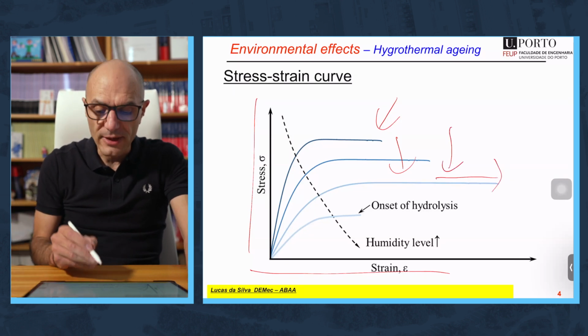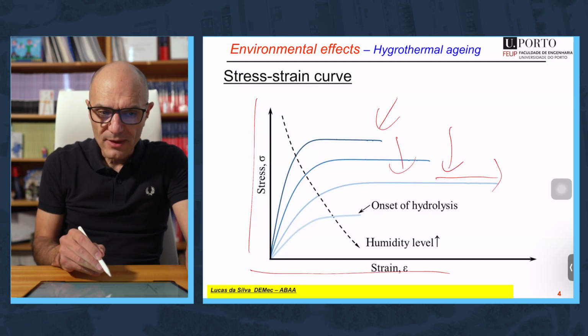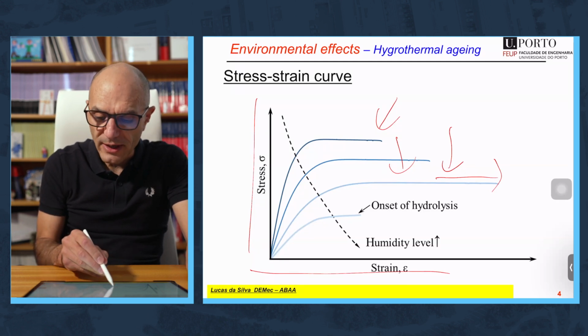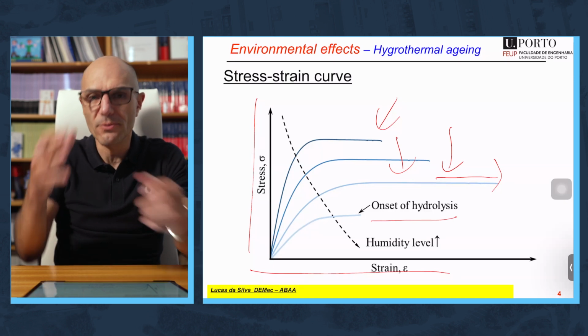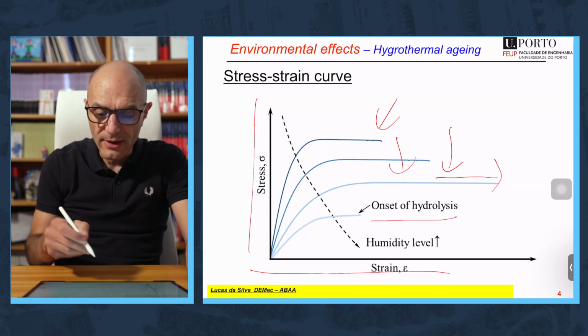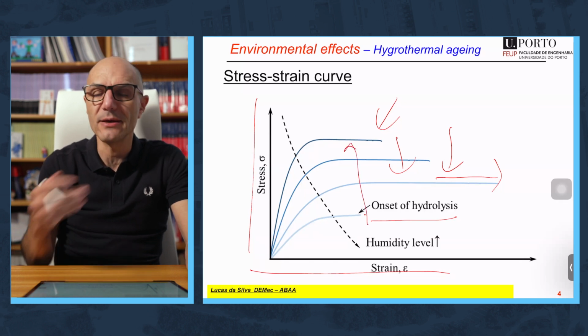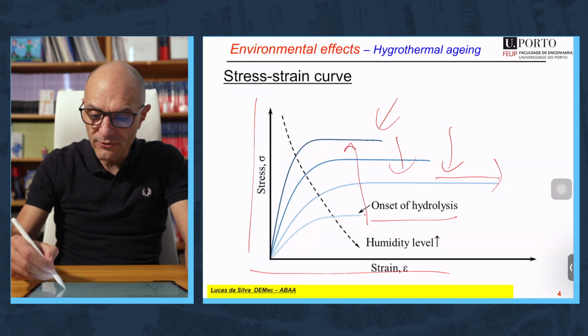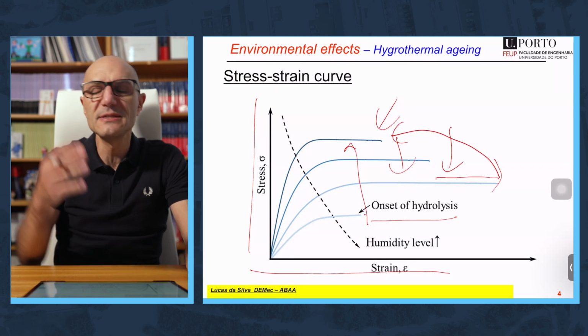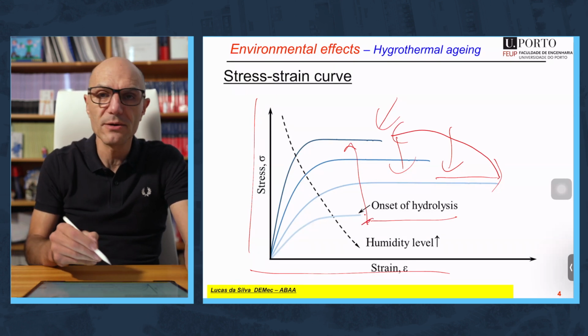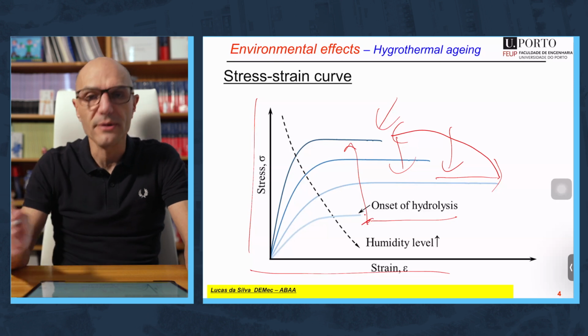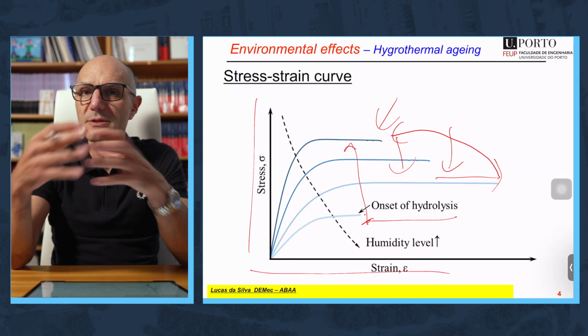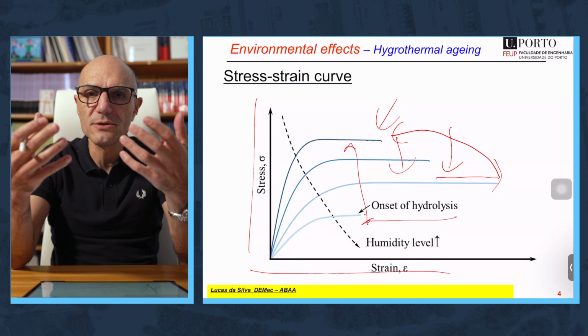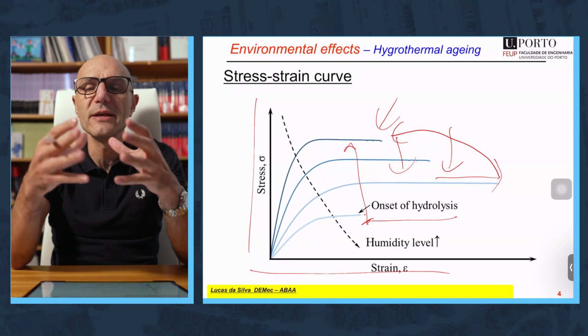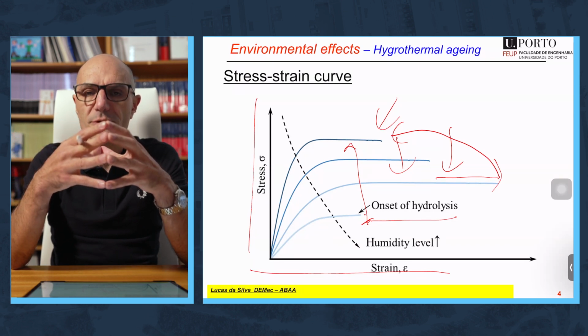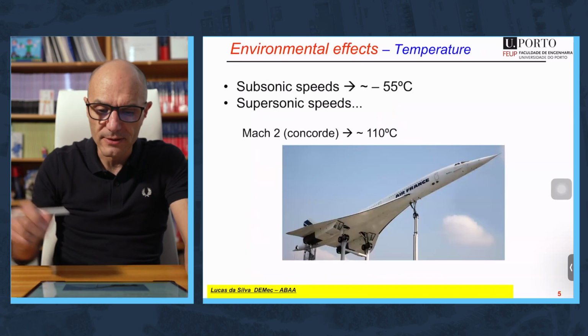But be careful, if you exaggerate, you might have chemical degradation of the adhesive caused by hydrolysis when the water breaks the molecules of the polymer. In that case, you cannot go back here by drying the adhesive. Here, if you dry, you can go back. It's called physical degradation. When you have chemical degradation, it's over. You cannot recover the adhesive. So a bit of water, it's not bad actually, because it increases the ductility, and we know that the ductility is very good for the joint strength. We have seen that in the joint design part.